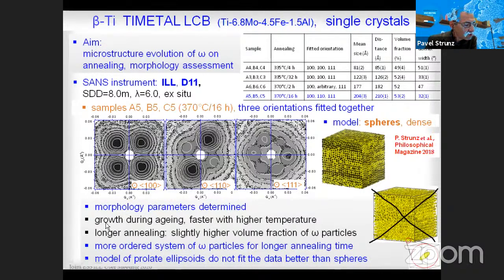I want to point out two things. First is that we obtain a more ordered system of omega particles for longer annealing times. And the second point is that the model of prolate ellipsoids doesn't fit the measured data better than the model of spheres. So the best fitting is the dense model of spheres.